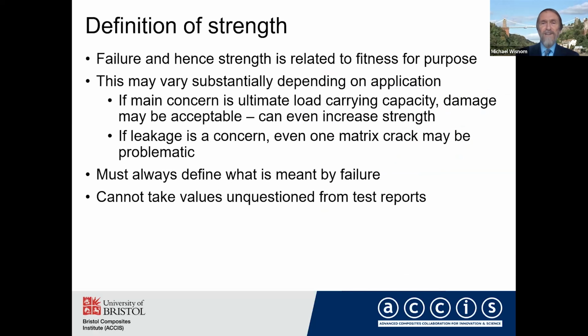So the definition of strength is really quite an important point, I think, and failure, and hence strength, is really related to fitness for purpose. And this may vary substantially depending on the application. So if the main concern is the ultimate load carrying capacity, then damage may be acceptable. It can even increase the strength. The splitting that you get, for example, at a notch helps to blunt the stress concentration and can actually increase the ultimate strength. On the other hand, if you've got a tank and you're worried about leakage, then even one matrix crack may be problematic in giving rise to leakage.